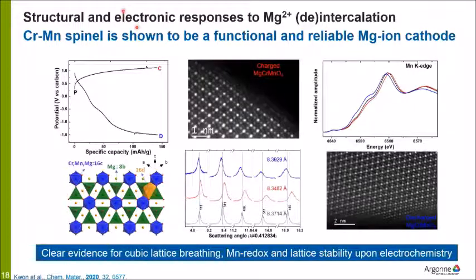So structural and electronic responses to magnesium in these solid solutions are shown to be achieved. And so once again, you can see we can look at the charge state under microscopy and look at the empty tetrahedral sites. We have evidence that magnesium has been removed from the structure. We have lattice strain through XRD showing reversible shifting, pristine, charge, discharge, and we do see the manganese K-edge reversibly shifting from charge to discharge state.